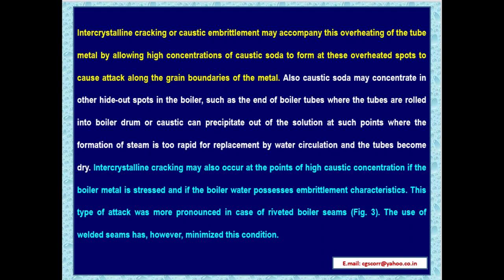Also, caustic soda may concentrate in other hideout spots in the boiler, such as the end of boiler tubes, where the tubes are rolled into the boiler drum, or caustic can precipitate out of the solution. At such points, the formation of steam is too rapid for replacement by water circulation and the tubes become dry.